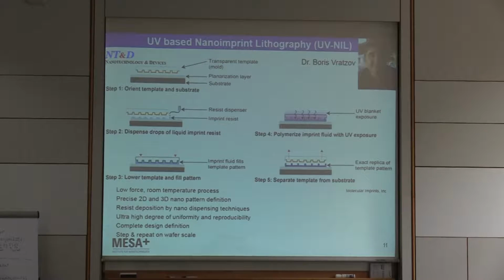So you have your template. Normally, you have to put an imprint resist, and you have to adjust the amount of imprint resist depending on the features on your stamp. So this is not completely trivial. There's an algorithm for how to dispense this. Then you imprint. In this particular kind of nano imprint lithography that we use, a UV curable resist. So you imprint, then you expose to UV, you cure the resist, and then you retract. That means that the stamp needs to be transparent for UV.